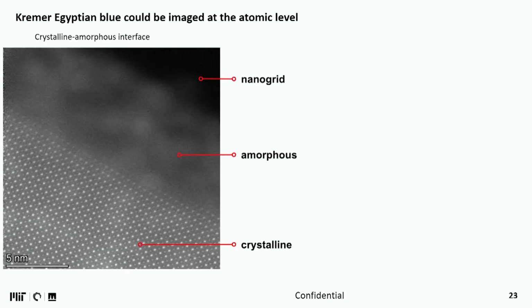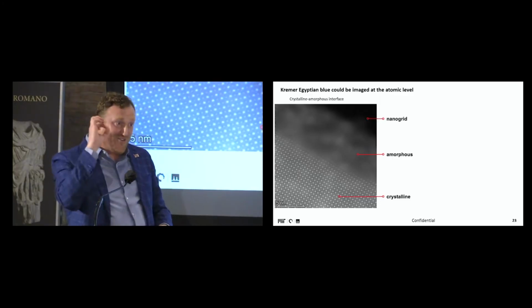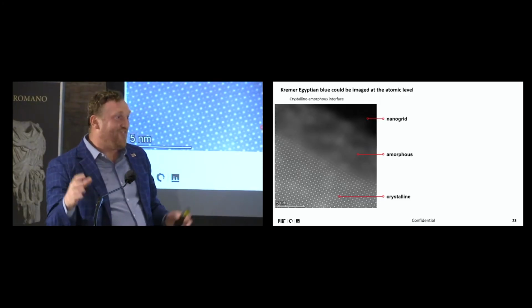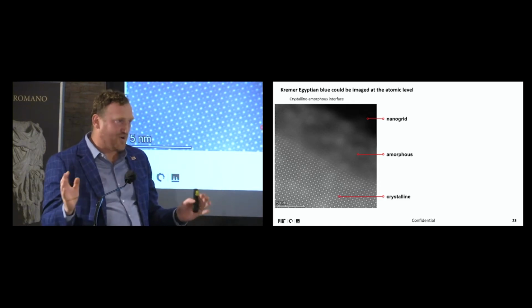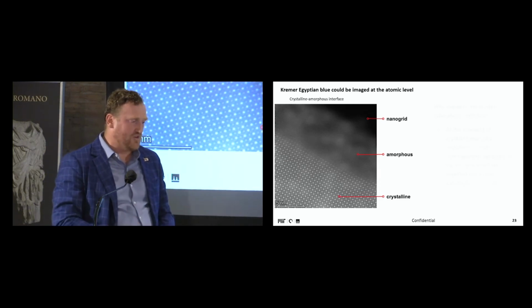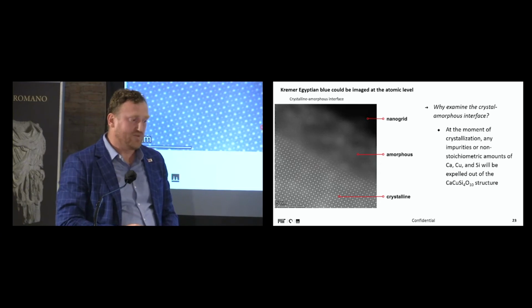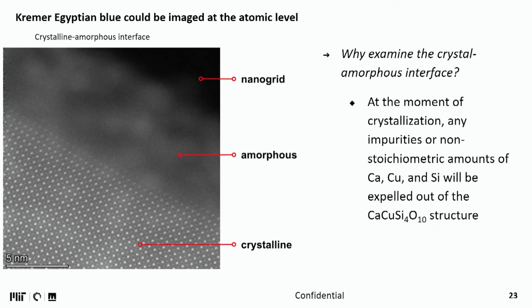And if we see it as still Egyptian blue, it means that this Egyptian blue was produced exactly at that moment of time, so T0. And now, if we assume that this amorphous is the glass, the trash that was expelled at the moment of crystallization, this might be an original time zero formula of our workshop. So we tried to do this, quantify which elements are there, for example, at this interface here.